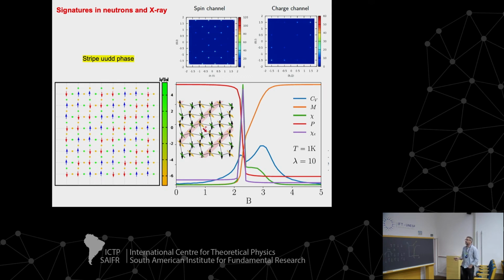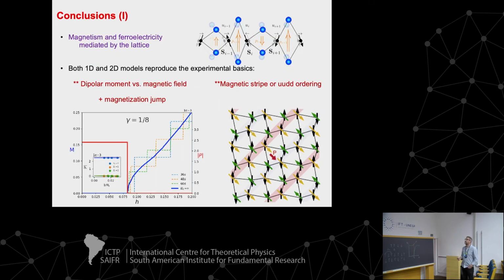And okay, so essentially the pattern is something like this. So short, long, in the two directions, in some particular way. And importantly, as in the 1D case here, the dipolar interactions are very important, which are usually disregarded, but precisely it is the dipolar interactions that select this particular ground state, which we call the striped one, because you can follow stripes of same-direction spins like here, and well, that's a particular name.